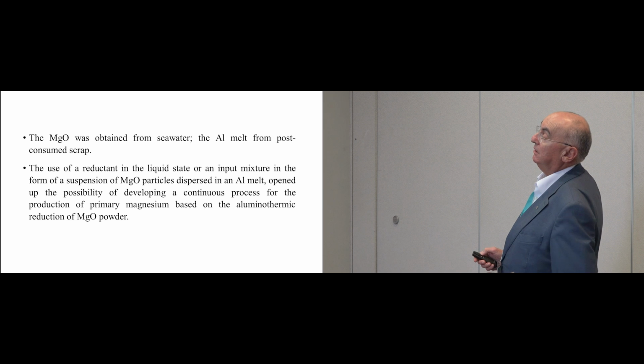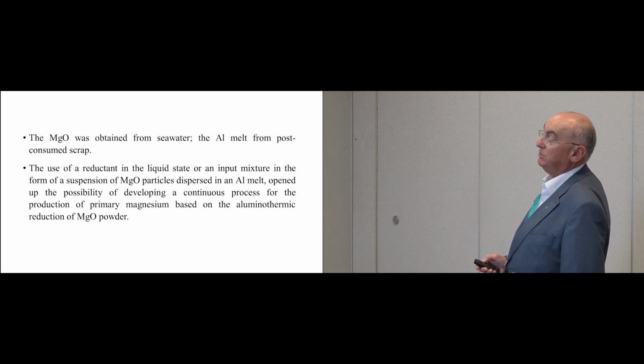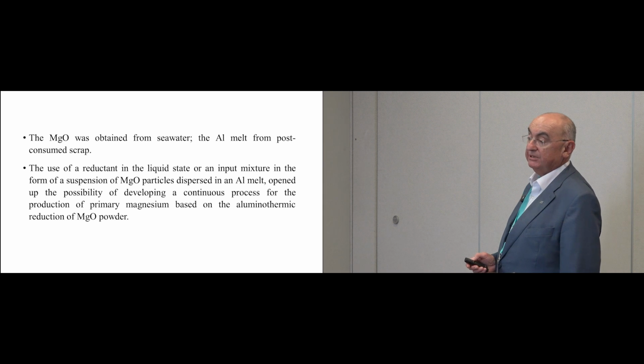Magnesium oxide is obtained from seawater. Aluminum melt comes from post-consumer scrap. Post-consumer scrap is scrap coming from end-of-life products with a footprint almost zero or very low. This means that under those conditions, the primary magnesium will be the green one, which is also a huge advantage.